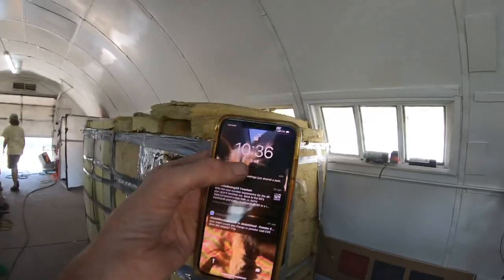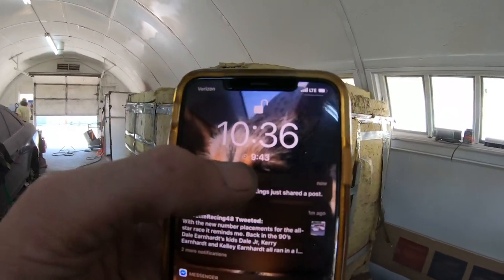Okay, so we have outgassed the wheels, or we are outgassing it. You can see there is 9 minutes, 40 seconds left. So we put the wheels in for about 45 minutes at 400 degrees. With our oven, with these size wheels, it takes about 12 to 15 minutes for them to get to temperature. And we turn it down to about 375, and it stays there until it's done for about 30 minutes or so.